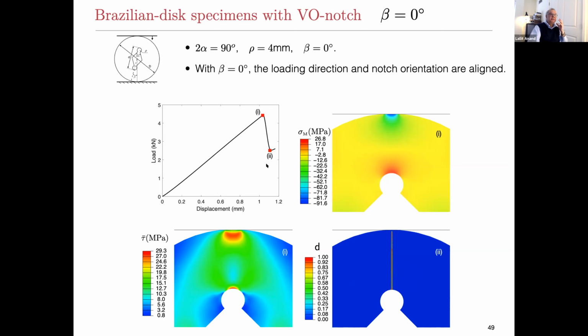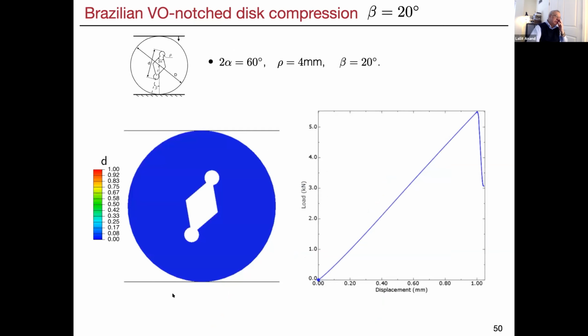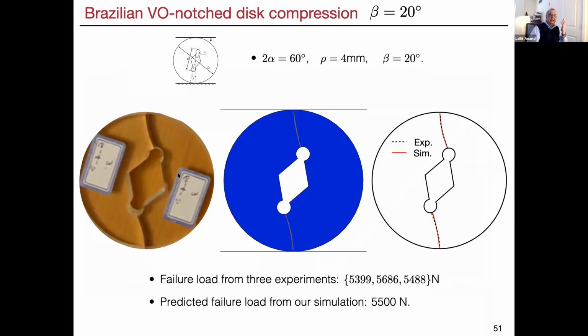What happens if the angle is different? Suppose it's 20 degrees. Now the question is, can we predict the path of this crack? What you see is the crack forms the way they form. They're not going straight, they're curved. It's a mixed mode type of failure. That's the prediction, but you can overlay their specimen with the numerical simulation, and you can see it very nicely predicts where the crack nucleates, the relative orientation, and also the propagation of the crack.